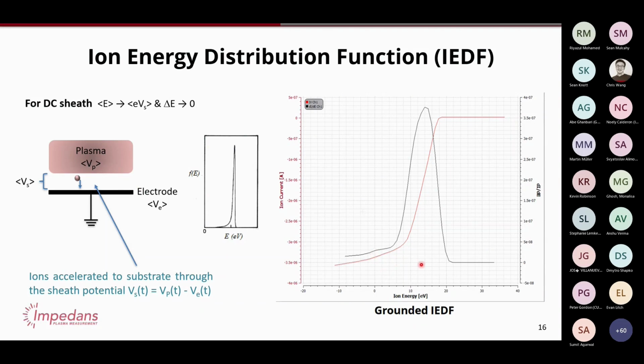Just to give you an idea of what these ion energy levels mean, depending on the material, let's say you're doing deposition and you're depositing a polymer or something. Maybe you need the plasma to do the chemistry, to produce the polymer that you want, or to activate the surface so the polymer sticks to it. You actually want your ions to be as low in energy as possible, because above a certain energy, they're going to start breaking the material that you're depositing, or they're going to start etching the material away. Even 15 eV for something as soft as a polymer, or some other similar materials, you're actually going to start etching and sputtering it away, or damaging it in some way.